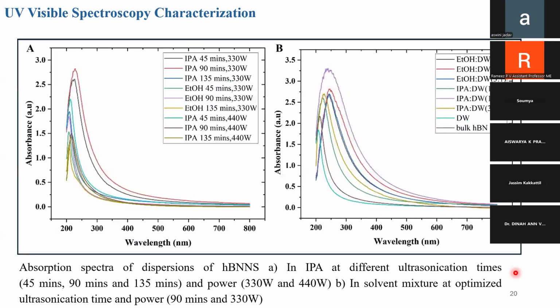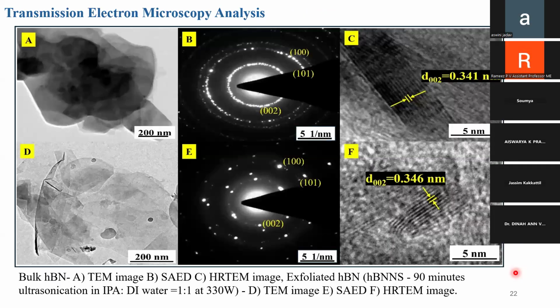yield percentages. Similarly, you can see this is the UV-visible spectroscopy, and these peaks give you the plots from which you can find the band gap of each HBNNS you got for each trial, and the size of the nanoparticles can even be predicted. And this is the transmission electron microscopy analysis. See, this is the bulk HBN, and here you can see the exfoliated HBNNS.